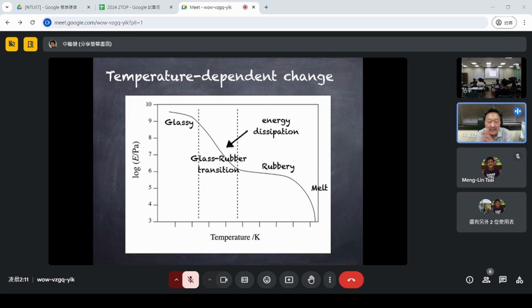But anyway, what we know is the temperature dependence of each material, and they have different transition temperatures. As I showed you in the movie, even in a rubbery state at room temperature, upon cooling down the modulus value increases, and finally it turns into the glassy state with a modulus value 1,000 times higher than the rubber. In this glass-rubber transition region, the modulus value is in between the gigapascal and megapascal level.